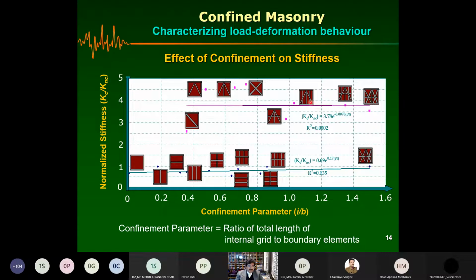And what we are doing is that at least you need the confinement from all around, and then internal confinement can add to your stiffness. If there's only horizontal, vertical, not continuing, there is a marginal improvement in the stiffness. But the moment you put the diagonals, then you increase the stiffness significantly. So if you want this stiffness, then you can add the diagonals. And if you want only confinement and not so much the increase in stiffness, because increase in stiffness means a decrease in the natural period.